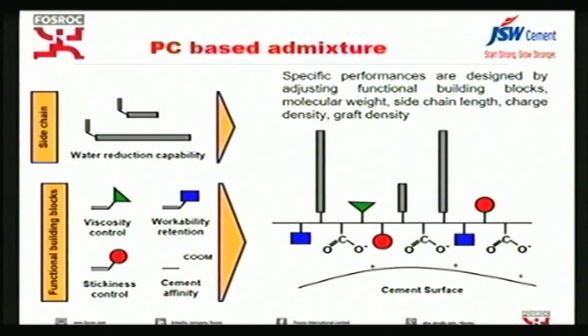Just to brief on this PC-based admixture, as I mentioned earlier, because of these functional blocks, now we can blend all the retarders and the VMA in a single admixture, and if anyone wants a separate retarder from the point of quality control, or a separate VMA, that is also available. But one point I stress here is, nowadays the PC-based admixtures available in the market are retarder and VMA. That was not the case earlier when the PC admixture was introduced into the market.